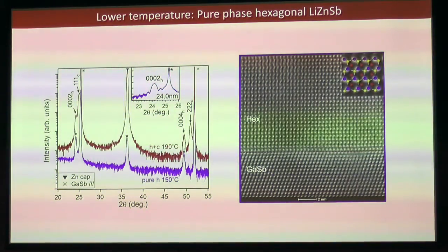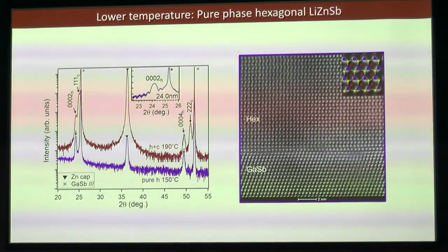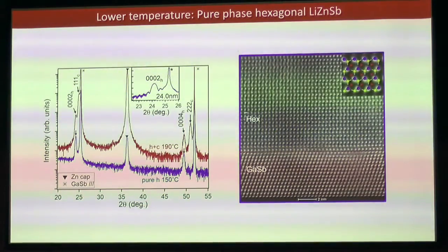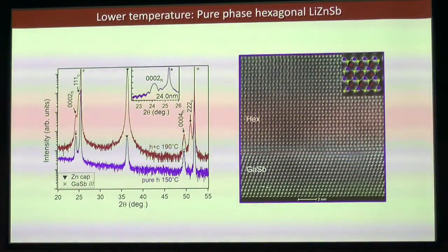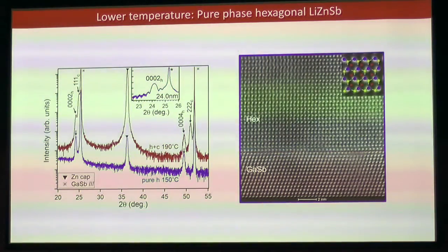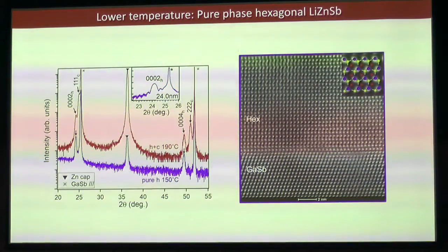We can grow what looks in X-ray diffraction to be pure phase hexagonal. We can confirm that it's hexagonal in the cross-sectional TEM. This time, it's the interface between hexagonal lithium zinc antimony and gallium antimonide. Interfaces are reasonably sharp, and we can see Kiessig fringes in the X-ray diffraction pattern.